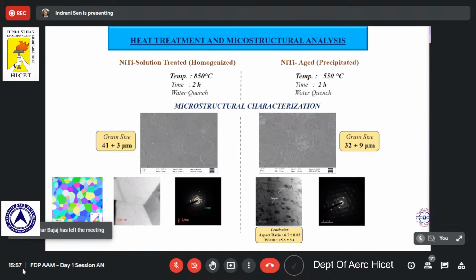Due to the aging, precipitate is a good agreement, but is strain-induced precipitate possible in SMA? Strain-induced precipitate, no. Strain-induced phase transformation can form, but strain cannot form precipitate as such. Due to the formation of precipitate, there could be some strain, but strain is not supposed to form a precipitate. For precipitate formation, you need to have a compositional disbalance. You need to do something with the heat treatment or so on.